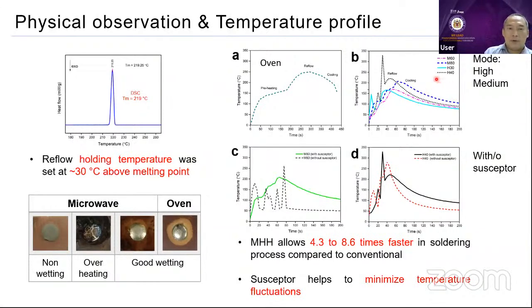So we found that one of the best is H40, H meaning high mode, and then 40 seconds. We also want to know what happens if we heat the sample with or without the susceptor, with or without the silicon wafer. If we are using the silicon wafer, we can have a very nice temperature curve. But without the susceptor, it tends to fluctuate.